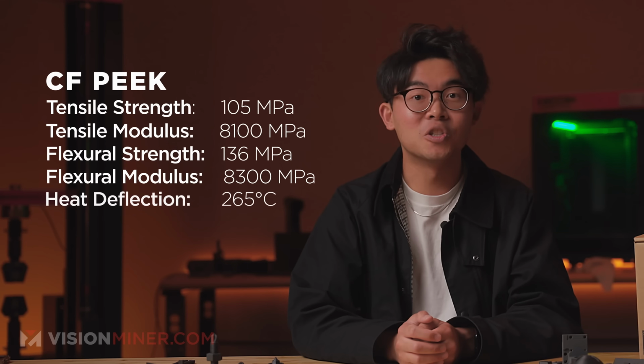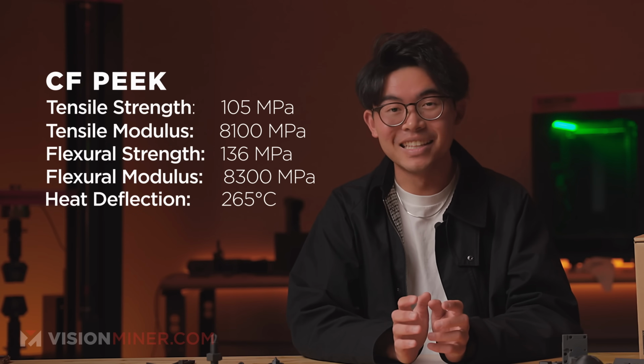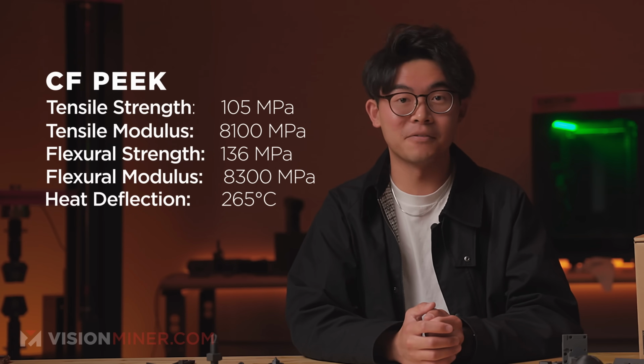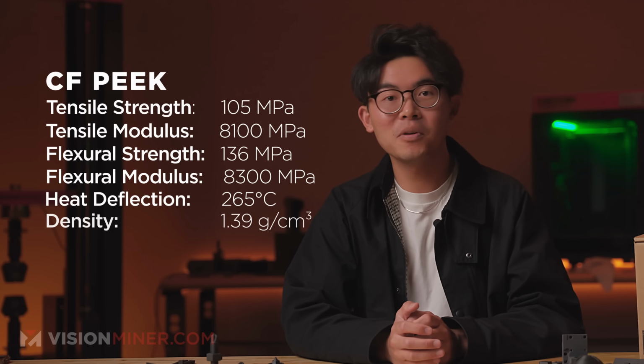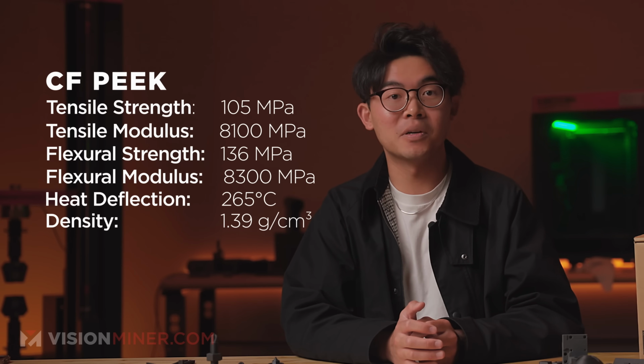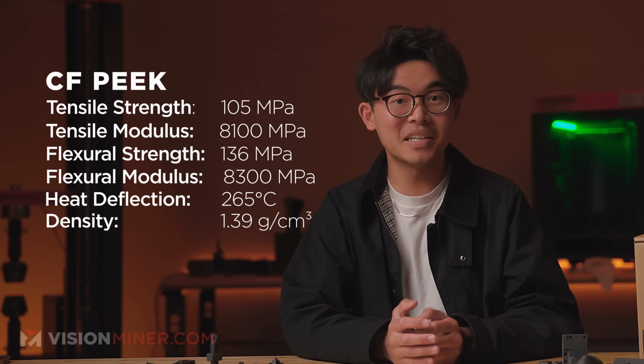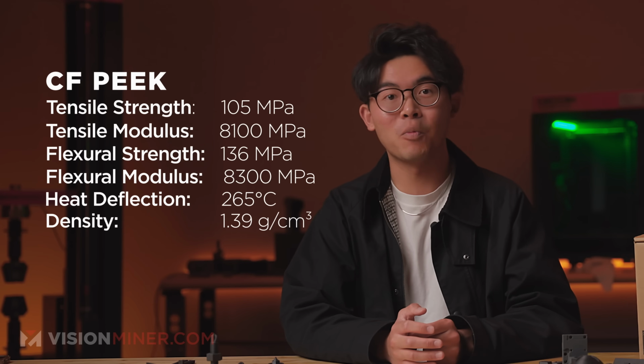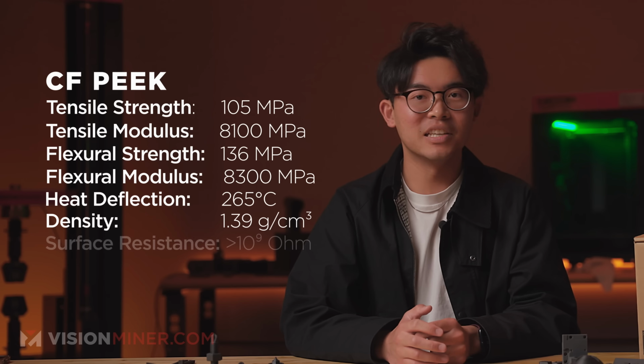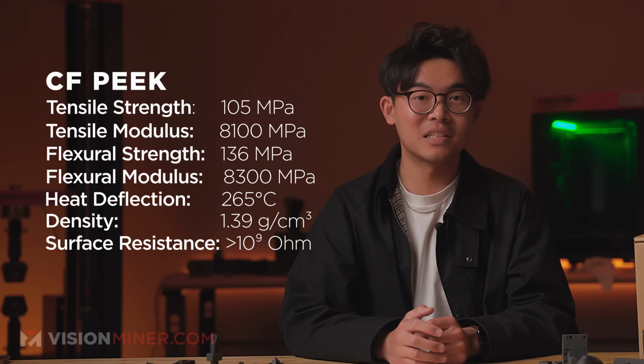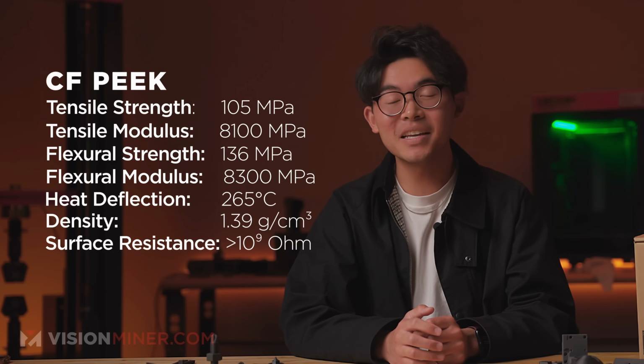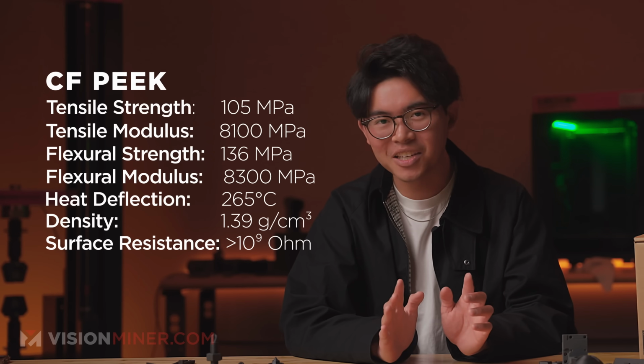Heat deflection temperature, 265 degrees Celsius. This is the temperature at which CFP begins to deform under load, making it highly heat resistant. Density, 1.39 grams per cubic centimeter. Despite being dense, CFP is actually much lighter than metal alternatives while maintaining impressive strength. CFP has a surface resistance of greater than 10 to the power of 9 ohms, making it suitable for ESD-safe applications. So how does CFP compare to regular PEEK?